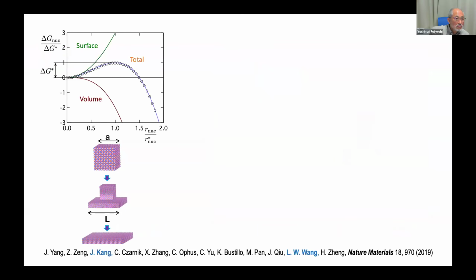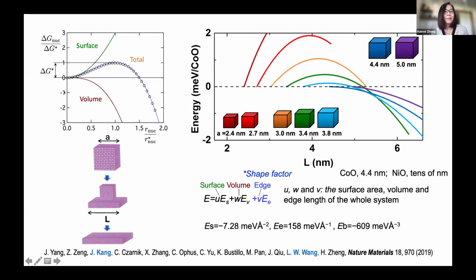Again, very briefly, considering this thermodynamic approach, if we consider this textbook type of classical theory from 3D to 2D type of transformation, this is not energetically favorable because the volume is the same. Then increasing this 2D growth would be introducing more energy. We collaborated with Dr. L. W. Wang, and he established a very simple model using these conventional surface and volume energy, and including a shape factor, and really beautifully explained this type of phenomena in this plot showing what we observed very clearly.